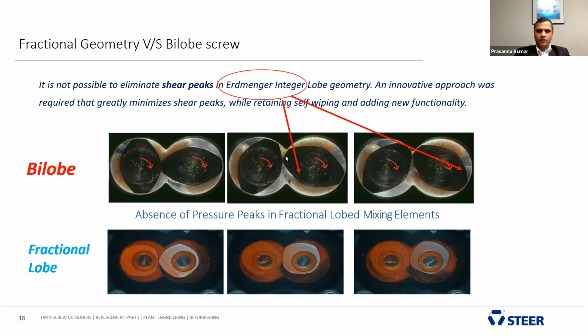So this fraction of the material is forced to go through the clearance between the elements. You can see the material going through here. Just imagine this extruder is running at very high RPM, and the shear rate developed for this fraction of material is very enormous and thus creates a degradation problem. You can also see black spots and black specks in your end product. So these are the disadvantages of the bilobe geometry.